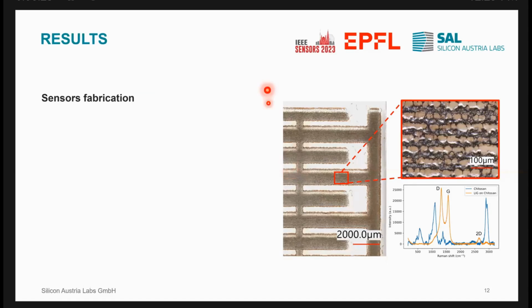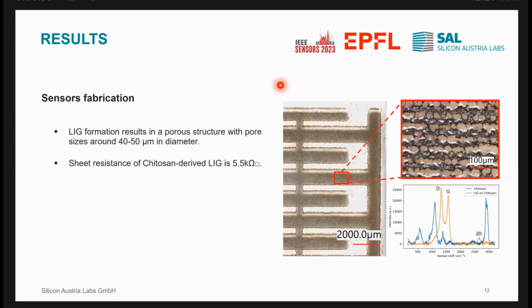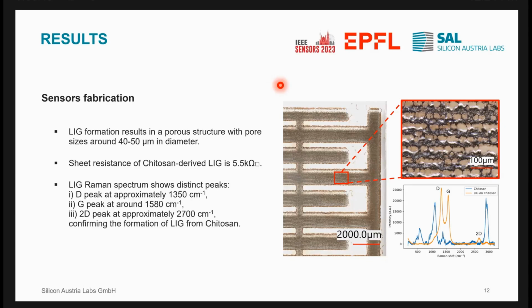Here you see on the right side a microscopy image of the LIG on Chitosan layer. The LIG formation results in a porous structure with pore sizes of around 40 to 50 micrometers in diameter. The overall sheet resistance of the Chitosan layer is 5.5 kilo ohms per square. And we did Raman spectroscopy, where you see the 3 distinct peaks for LIG formation: the D peak, the G peak, and the 2D peak. The blue line represents the Raman spectroscopy of the pure Chitosan, and the orange line represents the LIG on Chitosan.